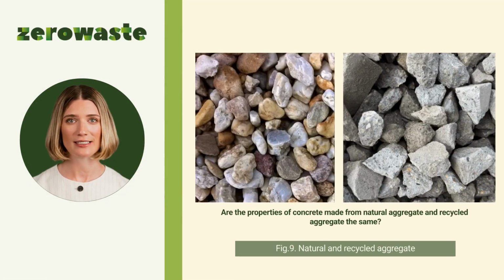Concrete made with natural aggregates and with recycled aggregates does not have identical properties. One of the most visible differences is density. Concrete with natural aggregate has a density of around 2,400 kilograms per cubic meter, while concrete with recycled aggregate averages about 2,250 kilograms per cubic meter, depending on the percentage of replacement. This reduction comes from the lower specific gravity of recycled aggregate and the higher air content in the mix. Another key difference is workability. Recycled concrete aggregate absorbs more water than natural aggregate, which reduces the ease of handling the mix. To improve this, recycled aggregate is often pre-saturated with water for at least 24 hours before use.